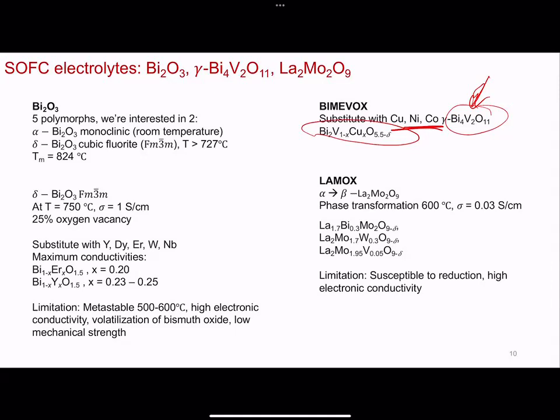And I can tell you all of these compounds suffer from the same challenges, which is, yes, the high ion conductivity phase works very well, but as soon as you start lowering the temperature a little bit, the materials start to destabilize. They will phase transform into other compounds, or they decompose into binary phases that are not ionically conductive. So that's the main issue with all of these.